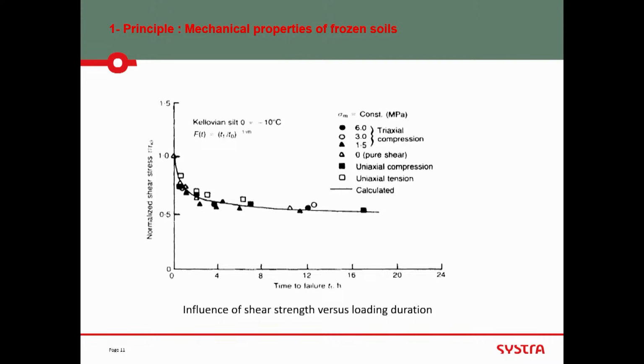What you can see is, so here, how do you read it? You read it from the following interpretation. Here is time to failure. And here is normalized shear stress, which is developed at failure. If you load it suddenly, in fact, what is the maximum shear stress which is developed? So you load it to failure suddenly. What is the load which shall be applied to load it to fail directly at t equals 1 second? Okay? By the load, you get the maximal shear stress. And this is normalized to this maximum shear stress.